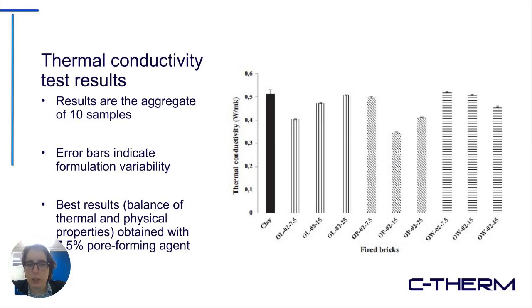So this slide shows the thermal conductivity test results, and specifically the effect of the pore forming agents on the effective thermal conductivity. And you can see also this plot has error bars, which indicates the relative variability of each of these formulations. The best results in terms of a balance of the measured thermal properties as well as the observed physical properties detailed in the paper were obtained with about a 7.5% by volume addition of a pore forming agent.